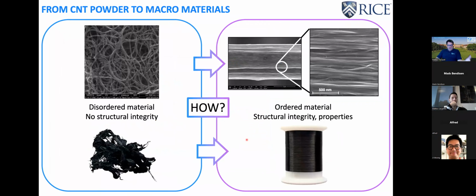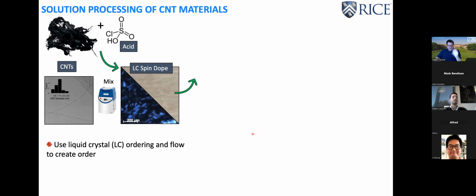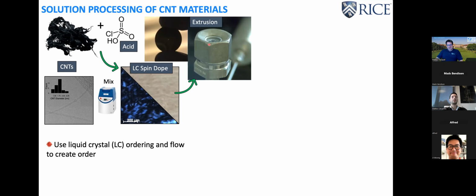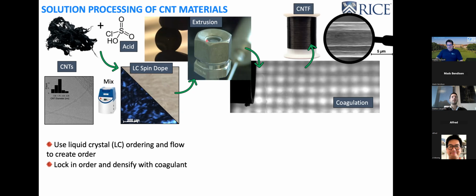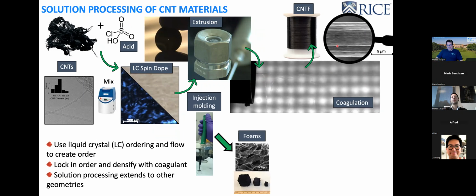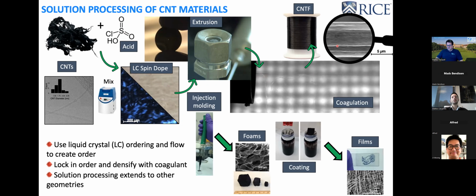Now, the next step is how to take this disordered material and make a fiber. And this is where my group has made most of their contribution in the last 20 years, which is by solution processing. So carbon nanotubes can be put in acids. They are natural solvents, and at sufficiently high concentration, they make a liquid crystal. We can then extrude it out of a spinneret, either a single hole or multiple holes, and it forms a fiber. And then the liquid dope is coagulated by using a non-solvent that removes the acid, and we're left with a fiber. So that's how we make this. It's possible also to make foams, films, coatings, and tapes.